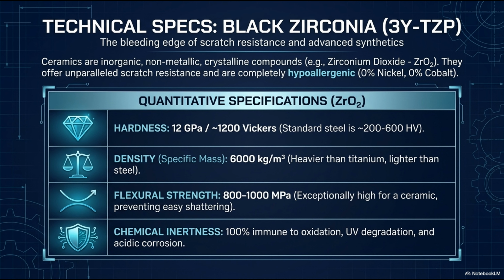Third, and most crucially, flexural strength. It registers between 800 and 1,000 megapascals. This is exceptionally high for a ceramic. Historical ceramics were incredibly brittle and shattered if dropped. Modern yttria-stabilized zirconia flexes microscopically to absorb shock, preventing easy shattering. Fourth, chemical inertness. It is 100% immune to oxidation, it laughs at UV degradation, and it is totally impervious to acidic corrosion from sweat or salt water. It will look exactly the same in 500 years as it does today.